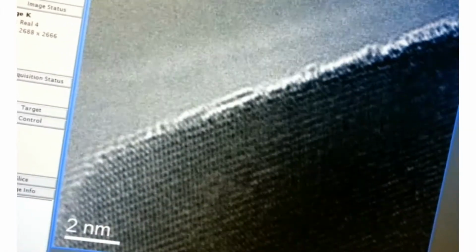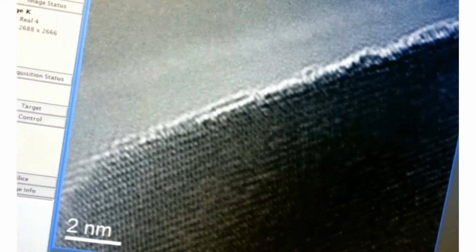I research materials called non-stoichiometric oxides, whose useful properties, such as electrical conductivity and catalytic activity, originate from their ability to exchange ions with their surroundings. For example, cerium dioxide exchanges lattice oxygen with gaseous oxygen by a reduction-oxidation reaction. Using the TEM, we can directly image this process, which causes atomic rearrangement at the surface of this nanocrystal during oxygen exchange.